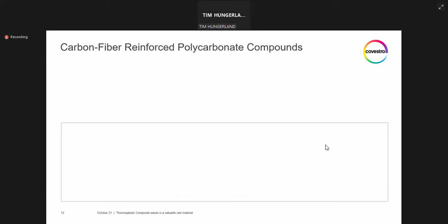The first thing to mention is that together with our partners, we have produced model compounds with 10%, 20%, and 30% in weight of fibers in order to test the property spectrum of carbon fiber reinforced polycarbonate. Also, all of the properties shown here and additional special needs for your application can be adjusted in the tailored product development. And another important message here is that in our lab tests and scale-up trials, we have found no significant performance differences between compounds made from recycled composites and those made from virgin carbon fibers.